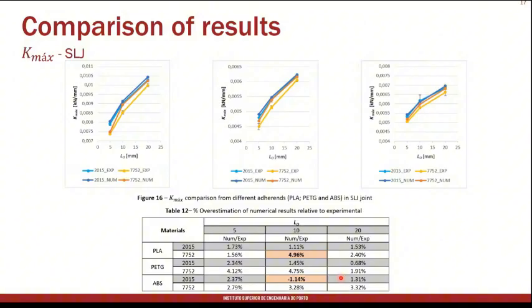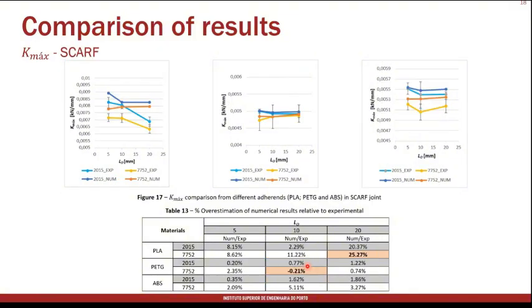In terms of stiffness of the joint as a whole, in terms of elastic stiffness of the P-delta curve, here we have an increase from 5 to 20 millimeters for all of the adherend types, and we have a maximum error of about 5% between the numerical simulation and the experimental data. For the scarf joint, we don't have a significant difference with the overlap length. We have significant standard deviation between experimental values, and we have errors that typically are not bigger than 10%, but we have 2 or 3 conditions in which we have a large error in this variable, which is also prone to error in the measurement.